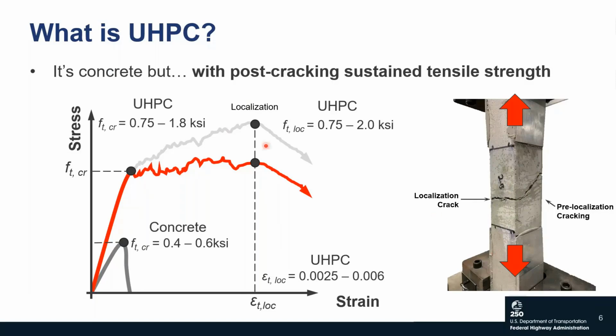The effective cracking stress, or the first cracking stress, of UHPC ranges between 0.75 KSI all the way up to 1.8. Crack localization stress starts at a minimum equal to the effective cracking strength, so about 0.75, and it can go up to 2 KSI. And the crack localization strain, that point beyond which you'll start losing tensile capacity, is about 0.0025 and can go up to 0.006.